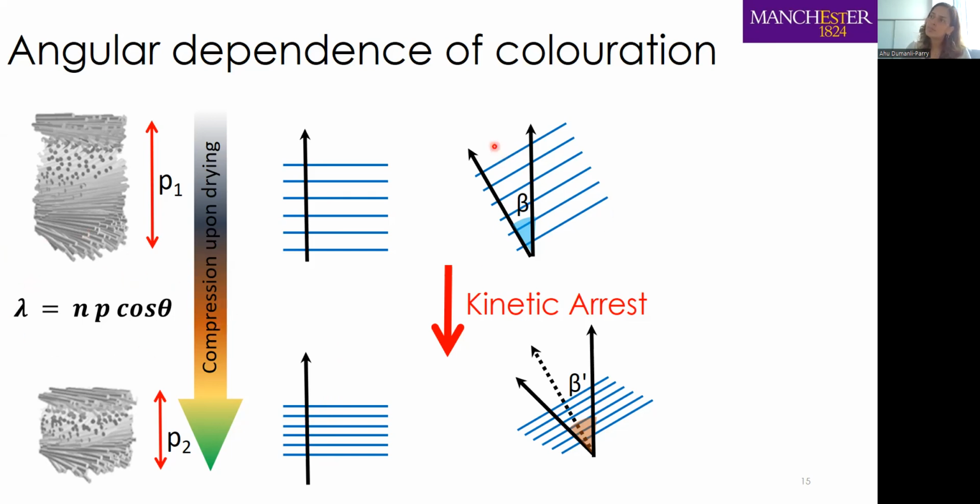But when you have tilted domains, because of the compression, the final contribution from that angle of the pitch is going to be much higher, which is undesired, and this also causes contamination, in terms of the completely left-handed circular polarization is not valid anymore, because if you have highly tilted domains, you will have more left and right circular polarization.